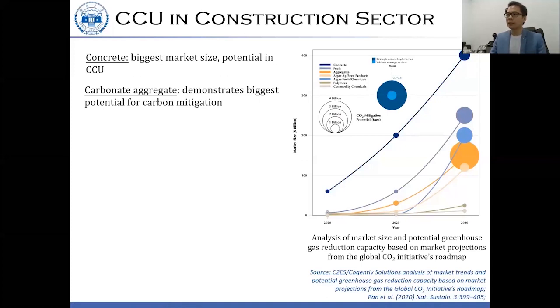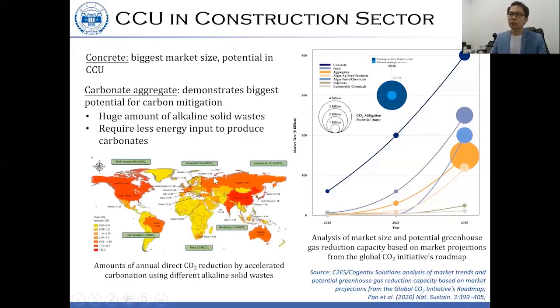So why does the carbonate aggregate show the biggest potential for carbon mitigation? They predicted that if the strategic action is implemented, it has the potential to mitigate 3.6 billion tons of CO2 by 2030. The key reason is that we have a huge amount of alkaline solid waste across different regions and countries. This material is a very good medium for CO2 sequestration and can be converted into carbonate product. And the whole process requires less energy input.